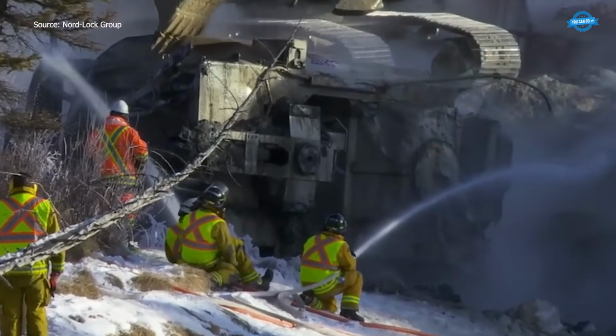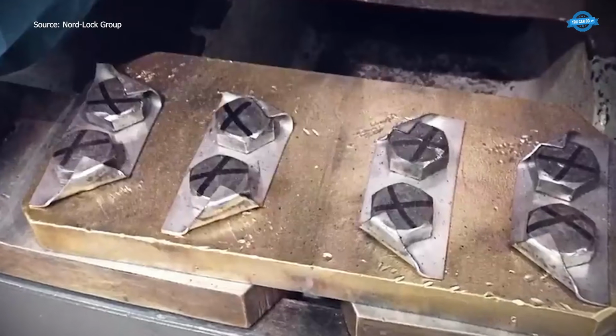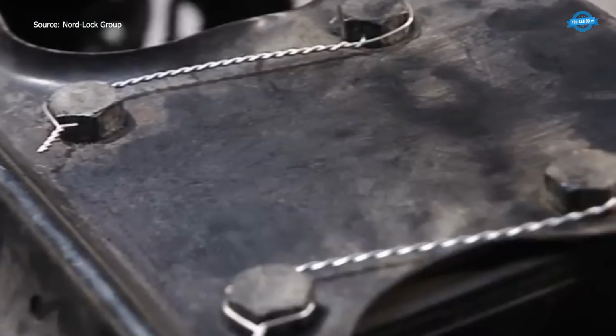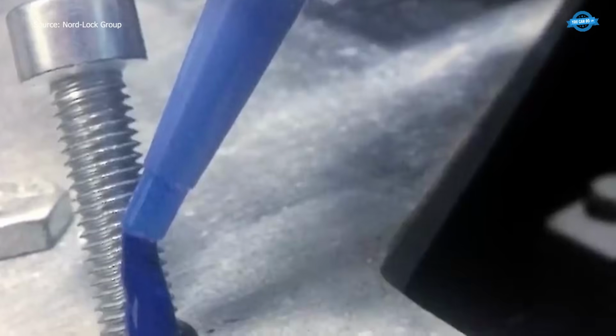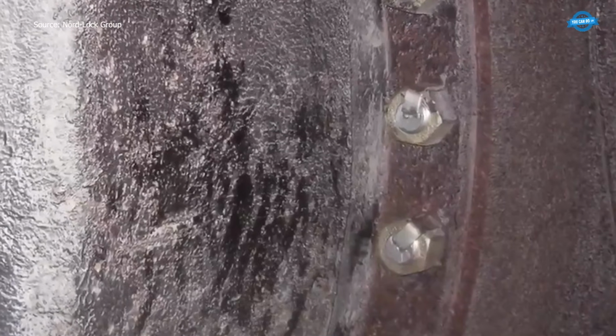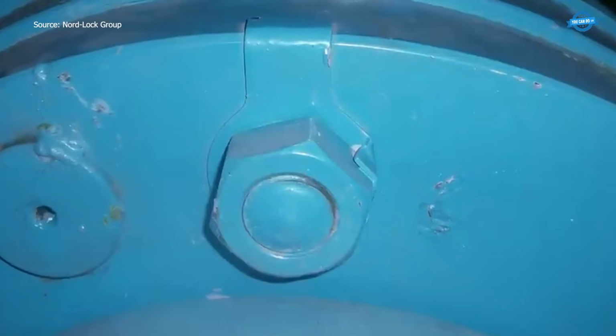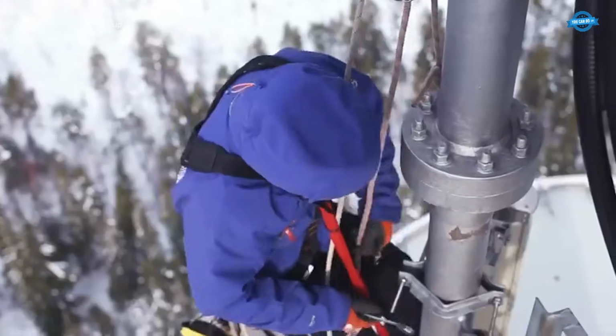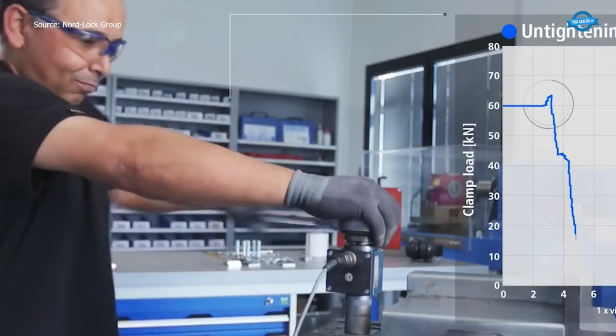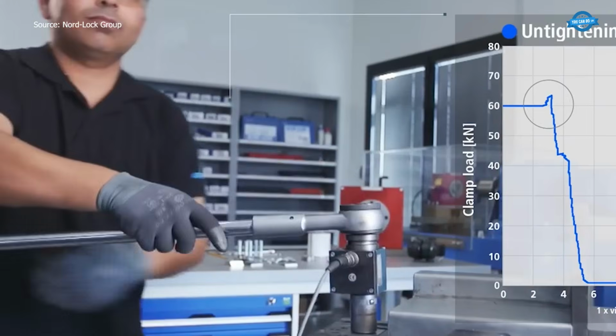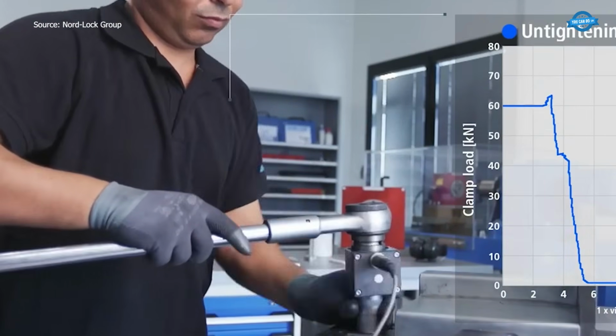Repeated cycles simulate years of vibration within a controlled window. This method exposes weaknesses fast, without relying on long timelines. That steady pull feels less like luck and more like engineered stubbornness. By the end of the Junker vibration test, the difference is clear. Nordlock wedge-locking washers keep joints secure when vibration becomes constant and unforgiving over time worldwide use.